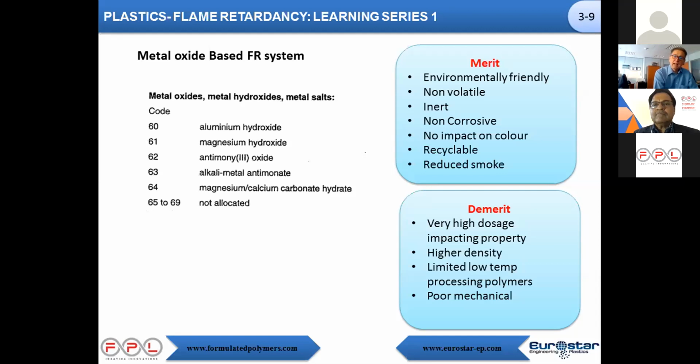You need a very high amount of flame retardant, mainly in the range of 40 to 50%. So it has an impact on properties, and it also has an impact on price per liter. So it's a very interesting material, but for the moment it's not a major one. We are selling in some applications with very stringent requirements, but I think in 10 years, maybe it will be the flame retardant that people will be using.